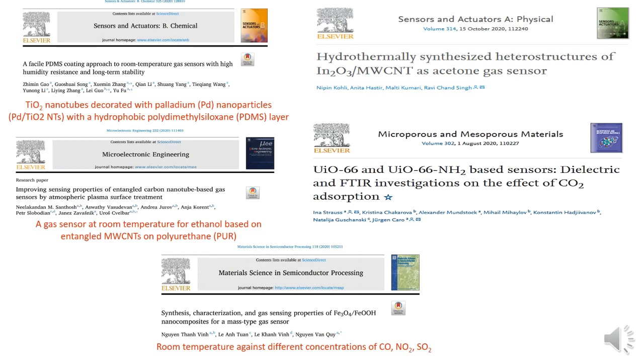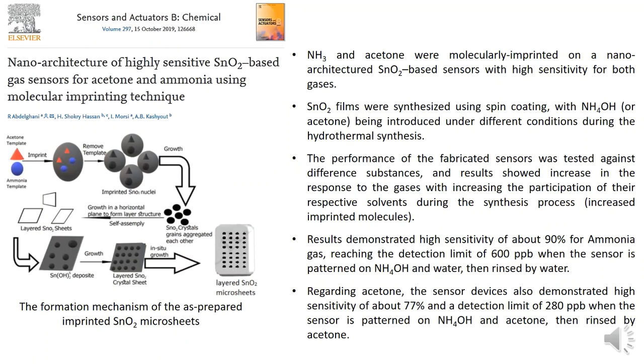And this is the general trend with different types of sensors, including biosensors, gas sensors, smoke sensors, and so on. Here is another interesting example of a gas sensor I would like to show you. In this study titled Nano Architecture of Highly Sensitive Tin Oxide-Based Gas Sensors for Acetone and Ammonia Using Molecular Imprinting Technique, the authors used the molecular imprinting technique by preparing a specific mold on the sensor substrate. They used an acetone template and an ammonia template, and so the sensor is ready to detect those two specific gases.